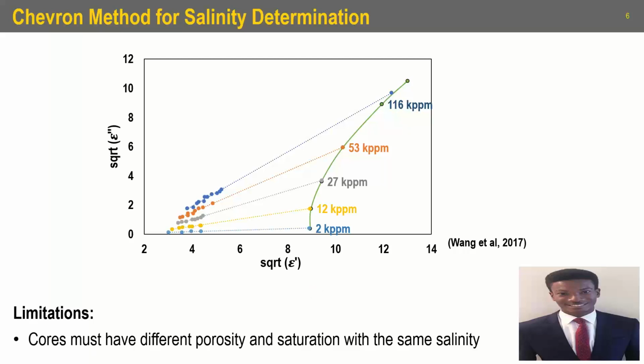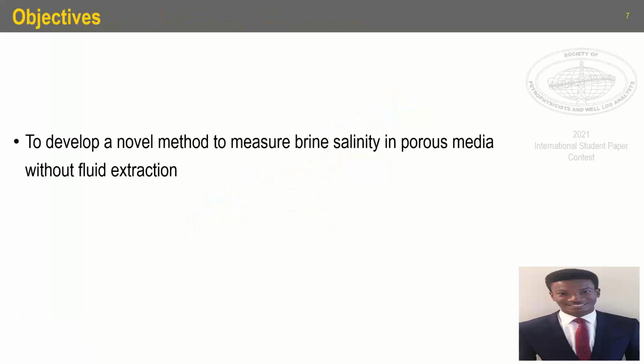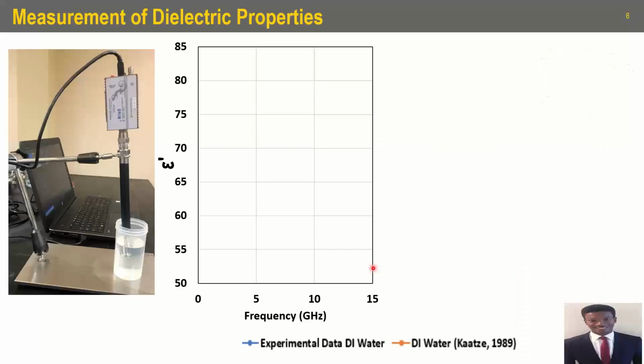So based on this, that leads to the objective of this presentation, which is to develop a novel methodology to measure brine salinity in porous media without fluid extraction. So here in this particular chart, we see how our dielectric measurements are conducted in our lab. We have a dielectric probe, and we place our sample under the probe, and then we make our dielectric